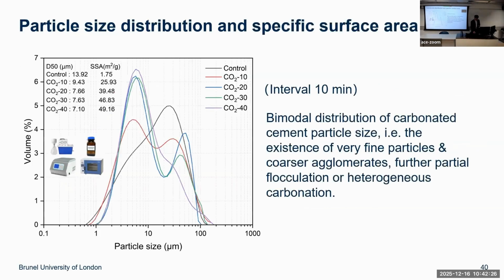In terms of particle size, after this carbon injection and aqueous carbonation, we found a bimodal distribution, with small particle size and also big particle size. So there are two peaks rather than just one peak. The smaller particles, which are good, are less than 30 micrometers; those are the non-detrimental particles. The later, bigger size is because of agglomeration. We don't want it, but it cannot be avoided.